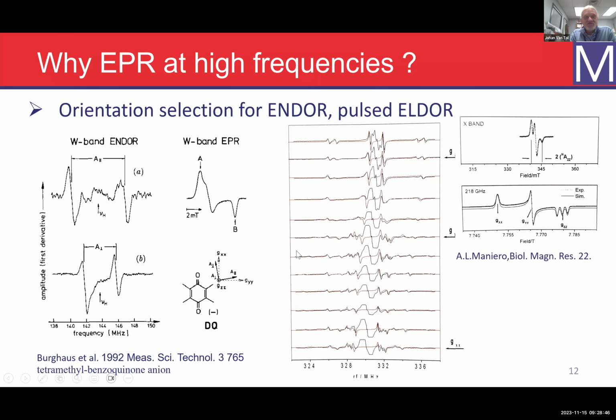Now, the orientational selection for ENDOR is kind of clear. So this is one of the first 95 gigahertz papers that came out of the Berlin group with Klaus Möbius. And they show an example of their ENDOR in some quinone system. So this is, I think, a tetramethyl quinone. The g-tensor at X band is not very well resolved, but if you go to 95 gigahertz, you can see it's much better resolved. And then you can do ENDOR on this side, or you can do it on this side. And you can see that the splittings are different, so you can resolve that. You can also go, this is done at 230 gigahertz or so. Actually 218, I think, if I remember well.